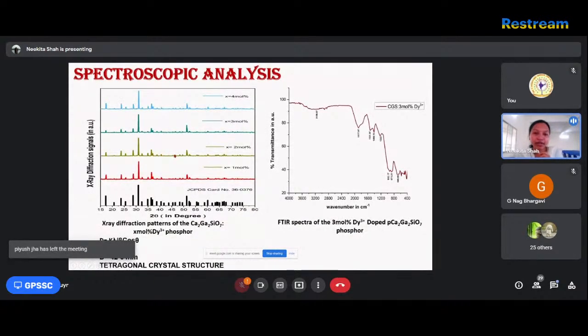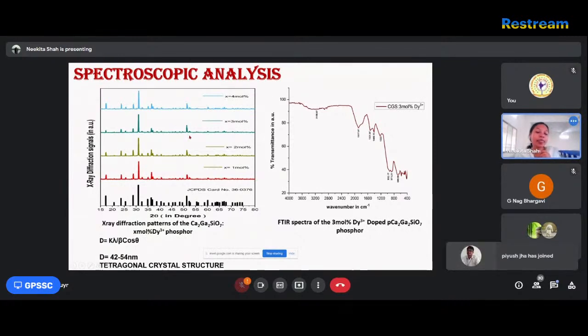These are the XRD patterns of the prepared material. Through XRD analysis of the phosphor material, we have concluded that all diffraction peaks of the material are well matched with the JCPDS file. So we can conclude that the prepared phosphor has a single phase.